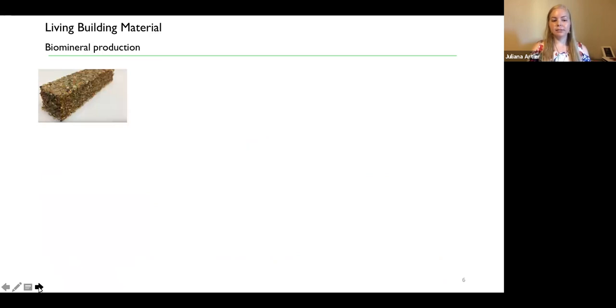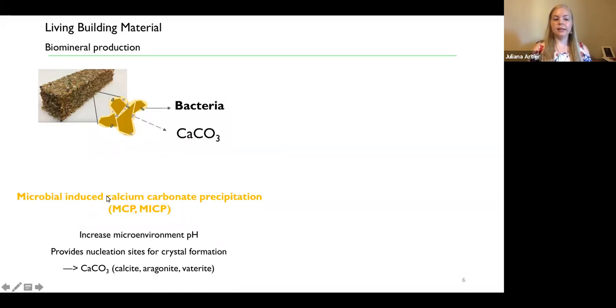The idea of our bricks uses biomaterials, in this case biominerals produced by bacteria. We know that several different types of bacteria can precipitate calcium carbonates, depending on the chemical conditions of the environment. The bacteria are important to induce calcium carbonate precipitation by increasing the microenvironment pH, and they also provide nucleation sites for crystal formation, which can yield different polymorphs of calcium carbonate, from calcite and aragonite to vaterite.